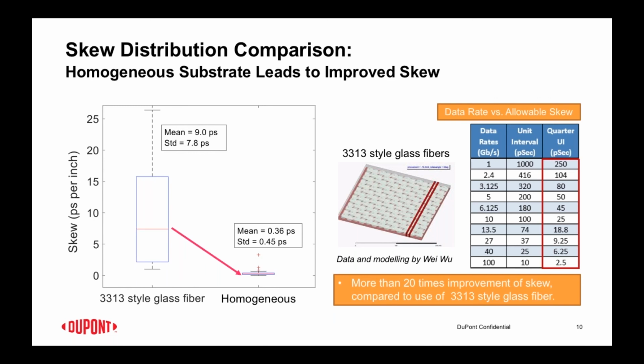The modeling, again, is a statistical representation shown in the graph, modeling the impact on skew by varying the position of the differential pair laterally across the substrate pictured for the glass reinforced laminate, as well as rotated from 0 to 45 degrees.